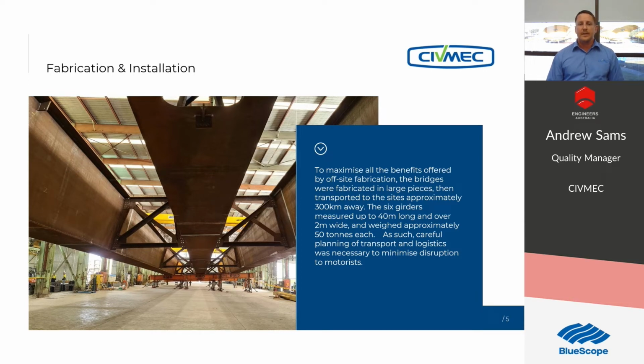I should probably note that a test plate was welded up using the Lincoln 81 Ni2 a few months before starting the welding on the bridge, and the plate was taken down to where the bridge site was located and left outside to see how the weld rust, the colour of it, matched the steel over time.